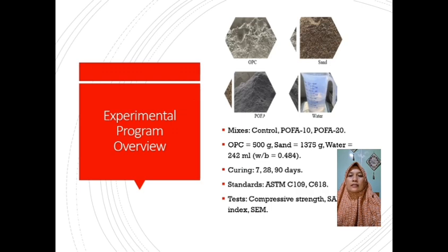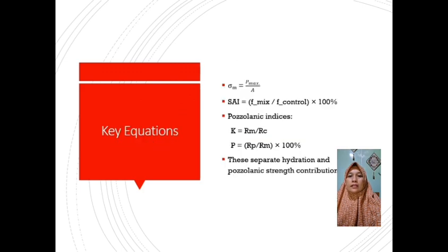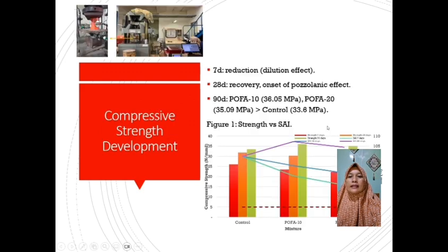Figure 1 presents the compressive strength trend. At 7 days, POFA mixtures show a slightly lower strength due to the dilution effect, less cement available for early hydration. However, by 90 days, both POFA mixtures surpassed the control.